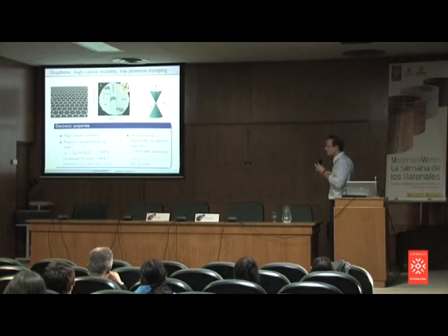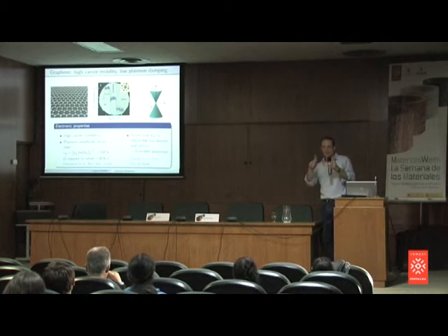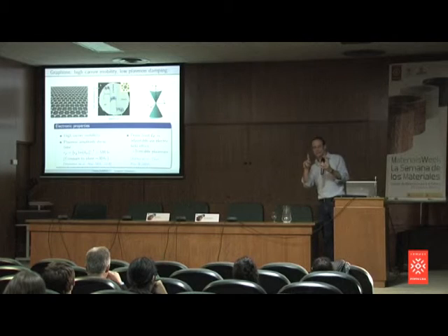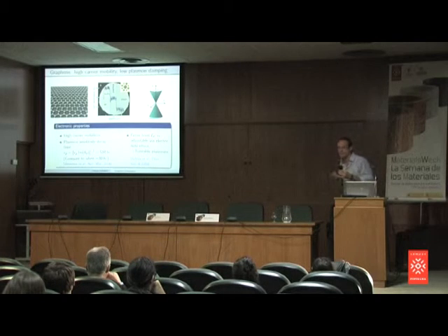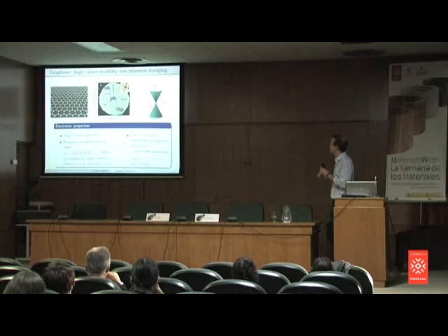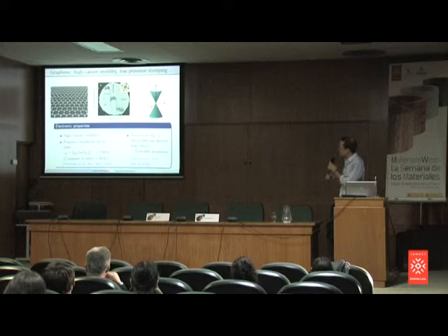And this is what we need for plasmonics. Why? Plasmonics wants to make electrons go like this, no? And if you want a charge oscillation like this, you don't want it to be damped out. And that's why you need mobilities. And that works. This is a recent article. That's from the ICFO now, from Koppens' group in Barcelona.